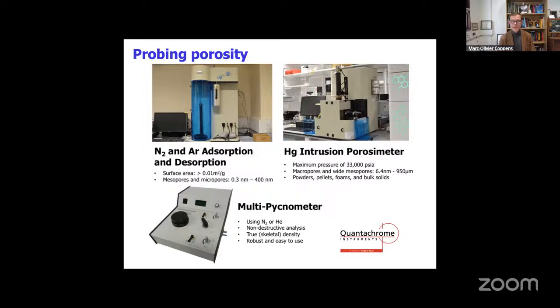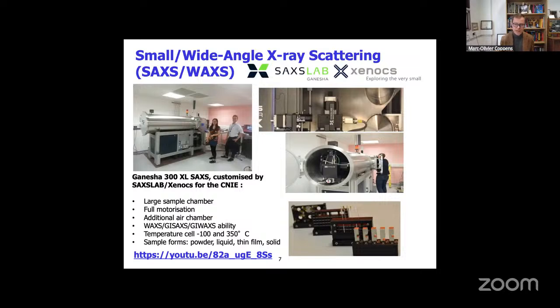Then there are other techniques, and these are some images from our own labs, about probing clearly the porosity, and this is something many of you use and work on. Adsorption techniques, adsorption and desorption of nitrogen, argon, other fluids, which can give us insights into the pore size distribution, especially for micro and mesopores, and then mercury intrusion porosimetry at larger scale, plus the overall porosimetry using pycnometry. There's small and wide-angle X-ray scattering techniques which give you a different perspective on these materials. Through the X-ray scattering, we can see how the material is organized. And these techniques can be used beyond crystalline materials, but also to test disordered materials, to investigate how rough, for example, particles are, as we will discuss later on.